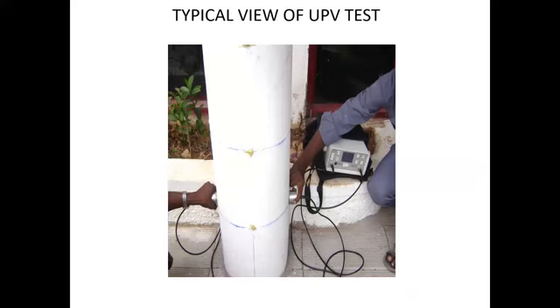The combination of rebound hammer and UPV helps us in identifying the corrosion-prone locations. For example, as was well explained by the earlier speaker, if corrosion is going to take place, obviously expansive forces are going to develop, and that pushes the cover concrete. As it pushes the cover concrete, when I do a rebound hammer test at that particular location, some amount of energy gets dissipated because of the gap between the concrete and the rebar, and you get a lower number. Similarly, as the gap exists between the rebar and the concrete, your UPV value is also going to be very low. In the other areas where the rebars are not there, you get a better value, and where the rebar is present, you get a lower value, and also a very low rebound number, obviously we can infer that corrosion has already initiated.